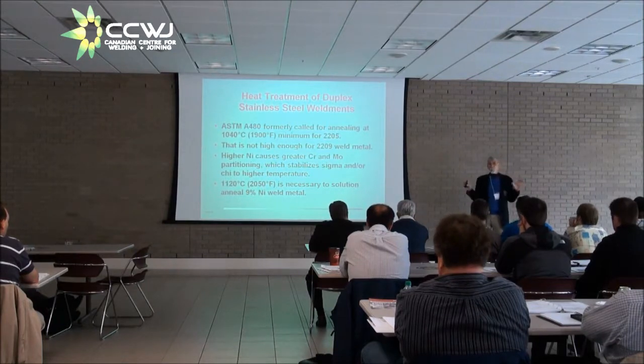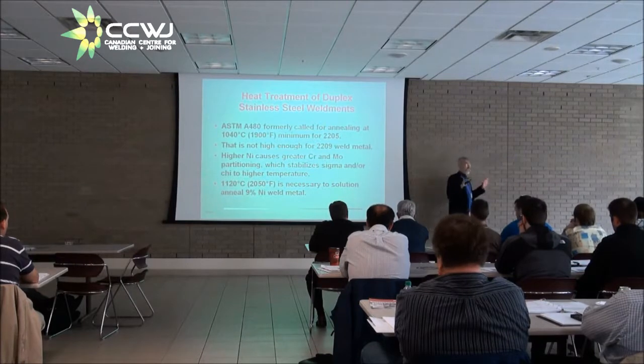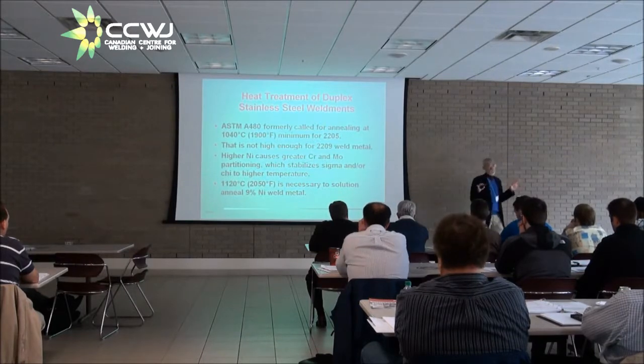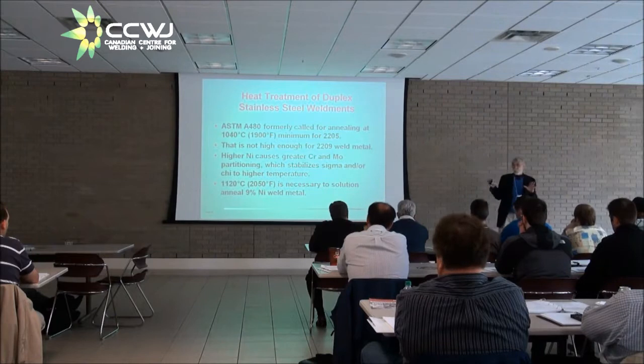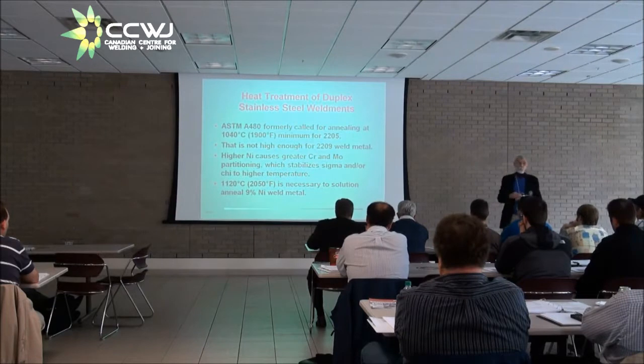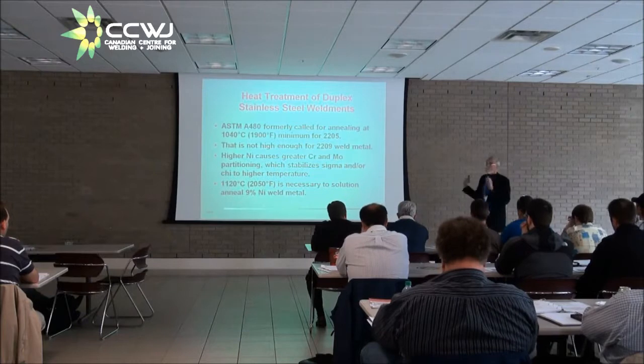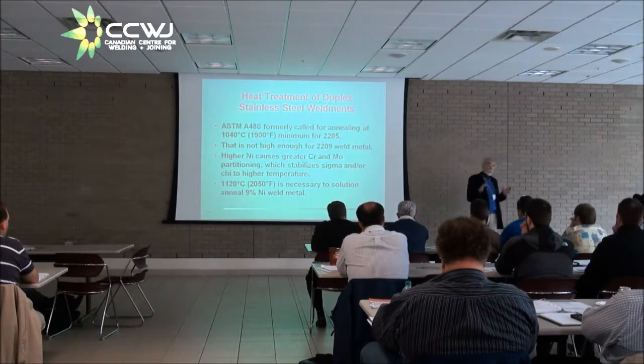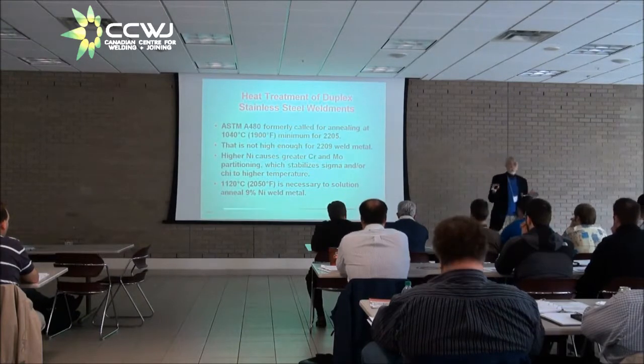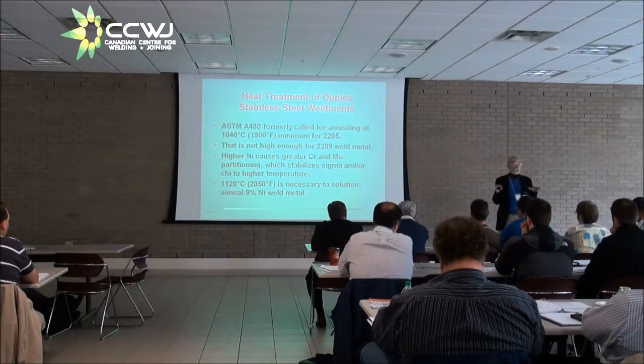And after they cold formed it, they saw some damage to the mechanical properties in terms of loss of toughness because of the plastic film. So they went to annealing. The annealing said 1040 degrees C minimum. So they went up to 1050 or 1060, I don't remember the exact number. Water quenched. Well, the head warped slightly during the annealing, so they needed to true it up a little bit.